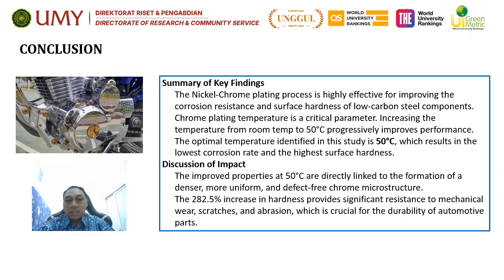The conclusion is the nickel-chrome plating process is highly effective for improving the corrosion resistance and surface hardness of low-carbon steel components. Chrome plating temperature is a critical parameter. Increasing the temperature from room temperature to 50 degrees Celsius progressively improves performance. The optimal temperature identified in this study is 50 degrees Celsius, which results in the lowest corrosion rate and the highest surface hardness.